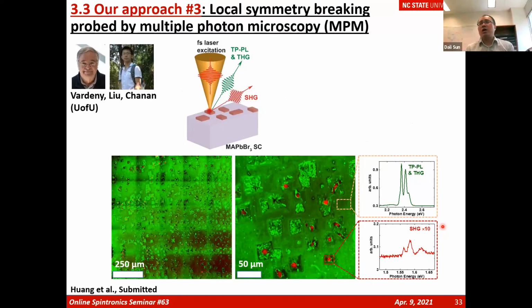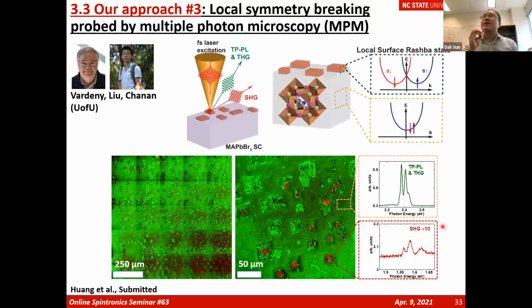We do a scanning across the whole crystal. Such a huge crystal, and only a certain spot, the red spot in the imaging, shows the symmetry breaking, the second harmonic generation. All the other areas, the green area, are third harmonic generation and photoluminescence, without any second harmonic generation, so they didn't contain any symmetry breaking. So this validates our hypothesis: local symmetry breaking only forms in a certain spot on the surface of the single crystal. That also explains why experimentally, by ARPES measurement, you are not likely to see such a response from the splitting band of the Rashba state. Because maybe you're unlucky, you're focusing your laser on a spot which didn't have local symmetry breaking.